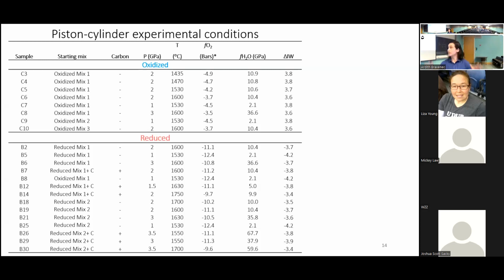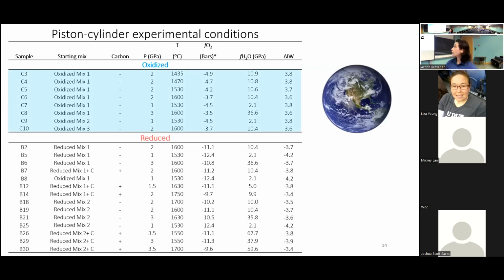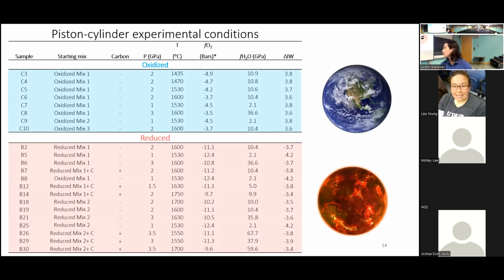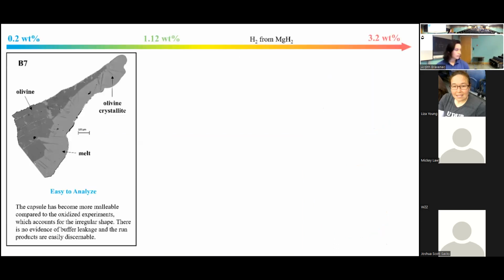All right, so to do that, I basically ran a whole bunch of experiments with different starting compositions at different pressures, temperatures, oxygen fugacities. But the big takeaway here is that I was running similar experiments in oxidized conditions, which are applicable to the Earth, to reduced conditions, which might represent these magma oceans. And here's what I found. So starting off, I started with some samples at lower water contents. That means I added about 0.2 weight% of hydrogen to the sample for reduced ones.